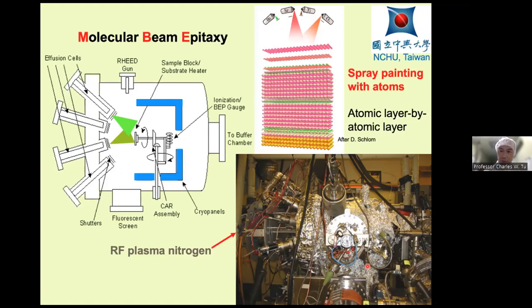And so we had to bake out the whole stainless steel system to about 200 degrees to drive out the water vapor, and then it can be pumped away. So that's the reason for the aluminum foil.